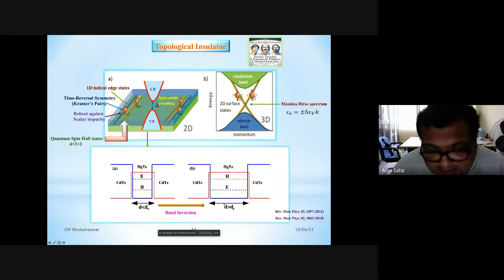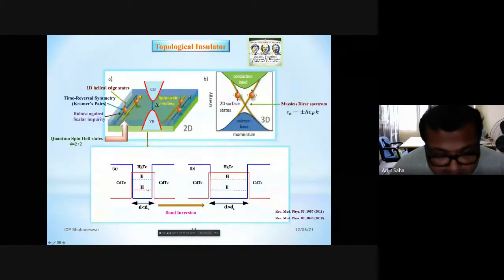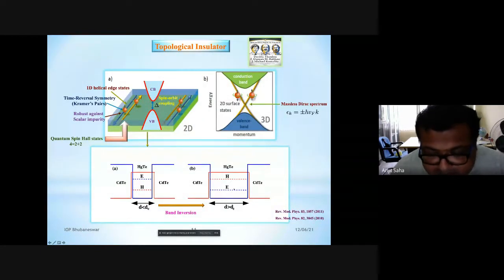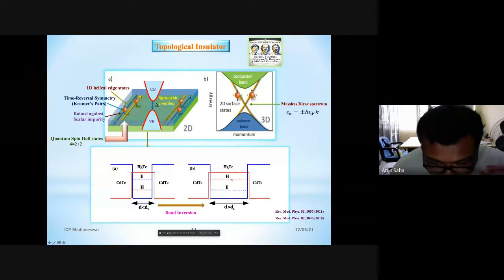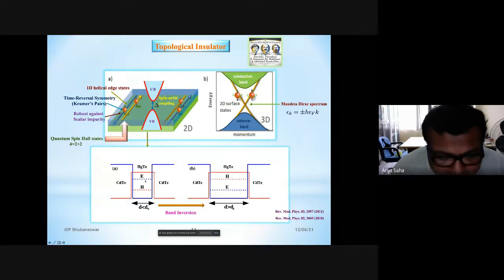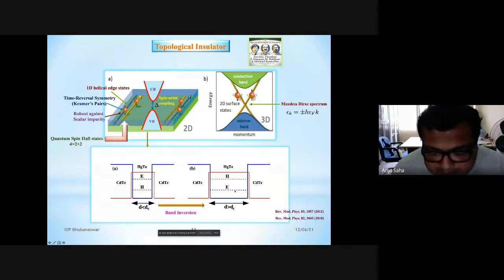So what happens is that with spin orbit coupling, your bands try to come close together. I mean, they come closer and closer, and after some critical thickness, they will invert. So what happens is that you will have a band inversion. That means you have a band gap which was, let's say, positive here, and the band gap becomes negative in that sense. So you have a band inversion. So when you have a band inversion in your band structure, this is the necessary mechanism to obtain this 2D topological insulator.